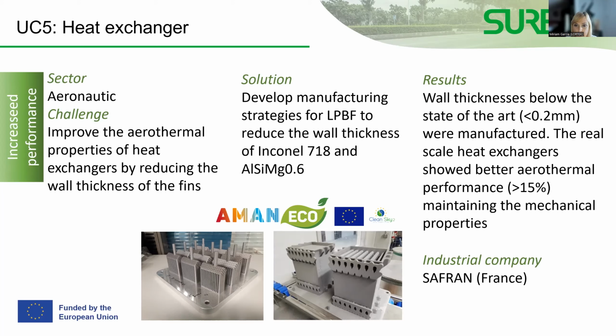And actually, the results were really amazing because we were able to reduce the thickness below the state of the art. We manufactured wall fins with a thickness below 0.2 millimeters for both materials. So it's a really good result because they are really thin. And with this, we then manufactured real scale heat exchangers. We tested them, we also simulated them, and we found that the aerothermal performance was increased by above 15% while keeping the same mechanical properties.